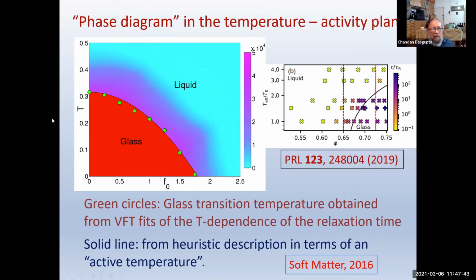If I now look at, let's say, fixed temperature and increased activity, then one would say an activity-induced transition from melting of the glass to the liquid state. These things were described in our Soft Matter paper, the first paper that we wrote on this. This simulation does give you something similar to what one is finding in experiments. But then one wants to understand this phase boundary. Is it possible to get some kind of theory which will tell you how the glass transition temperature depends on the strength of the activity?